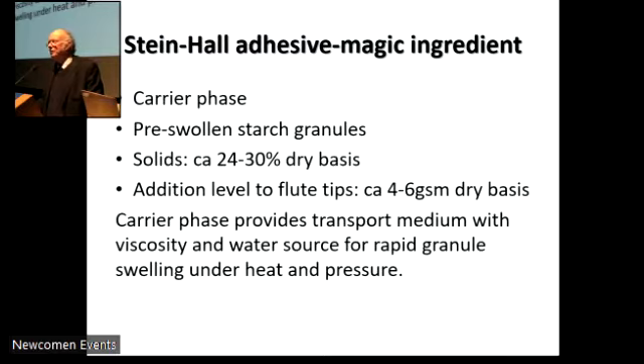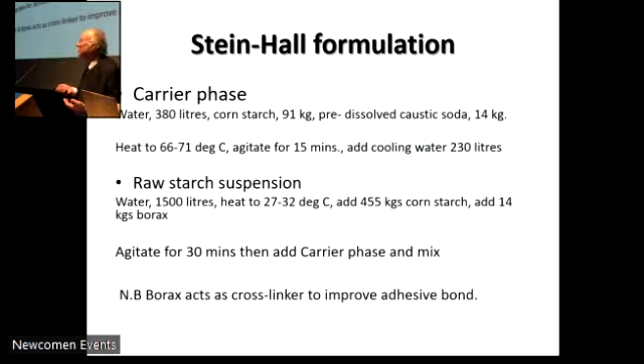And that's popular with the corrugator operators because, of course, the further you can make the glue go, the cheaper it is. And the carrier phase provides not only a transport medium to suspend the starch granules, but also a water source for rapid granule swelling under the heat and pressure of the corrugator nip. I won't go into this in great detail, but the carrier phase you make up out of starch, water, and some caustic soda, an alkali, to completely disperse the starch. And you mix that to a suspension of raw starch in water. You also, at one time, used to add borax, and the borax acts as a cross-linking agent to improve the adhesive strength. Because of environmental considerations in recycling, borax is not as popular as it used to be, and various synthetic additives may be put in.